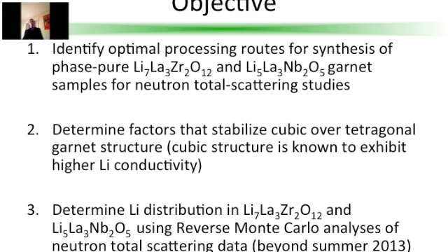So the focus of my project was to first identify the optimal processing routes for synthesizing phase-pure lithium lanthanum zirconate and lithium lanthanum niobate. Basically, I first had to find out how to make them. I then had to determine what factors stabilize the two materials in the cubic garnet structure as opposed to the tetragonal structure. And I had to do this because it's known that cubic garnets exhibit a much higher lithium-ion conductivity than tetragonal garnets. And when you're dealing with electrolytes, you want to have the highest lithium-ion conductivity for obvious reasons.